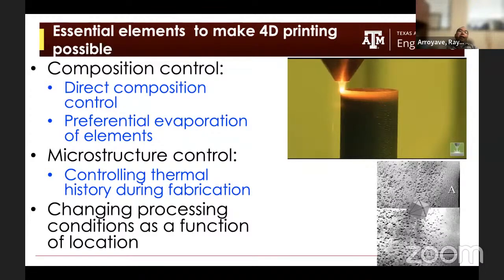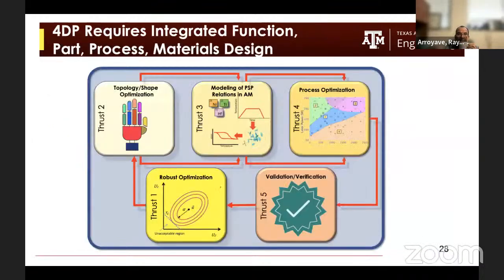And of course, in addition to composition control, we could do microstructure control, and this could be enabled, for example, by controlling the thermal history of the material during fabrication. So the key idea here is to change processing conditions as a function of location in the part.